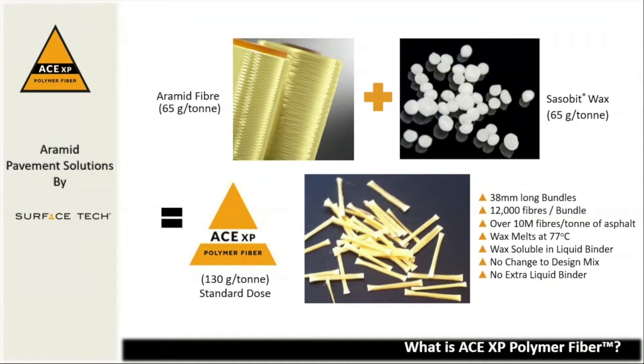Several spools of Aramid are pulled together to combine 12,000 individual fibers into each bundle before it is coated with the wax and then cut to a length of 38 millimeters. The wax melts at 77 degrees Celsius, releasing the Aramid fiber almost immediately when mixed in with the heated aggregate and RAP. As the wax melts, over 10 million fibers are released in every ton of asphalt mix produced. Sasobit becomes fully soluble in liquid asphalt binder, and it will not show up in the final mix. The volumetric properties of the original asphalt mix design are not in any way changed with the addition of ACE-XP.